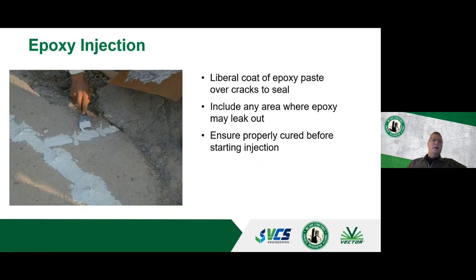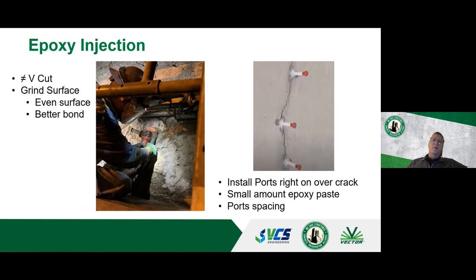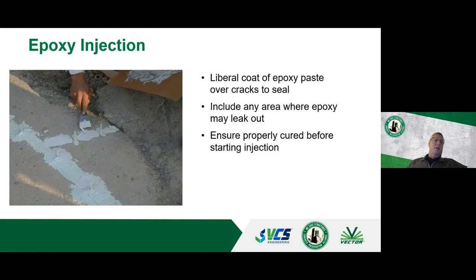The next part is, so you apply those ports. When you're applying those ports, you're using a small amount of epoxy paste to be able to put those over the top. Next, you're coming along and you're using that epoxy paste to cover the entire crack.